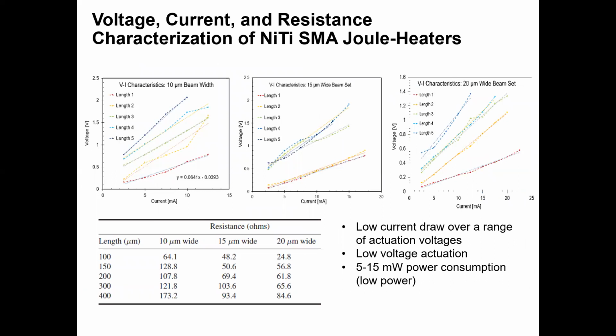So in order to further characterize the electrical performance of the various SMA MEMS Joule-Heaters, voltage current sweeps were generated for the different geometry devices. This allowed for calculation of the device resistance, which was a useful parameter to feed into some additional Joule heating simulations in COMSOL. Based on these characterizations, the current draw was rather low. It ranged anywhere from about 2 milliamps up to 15 or 20 milliamps, but depended on the applied voltage load. This would mean that the power draw is also quite low.